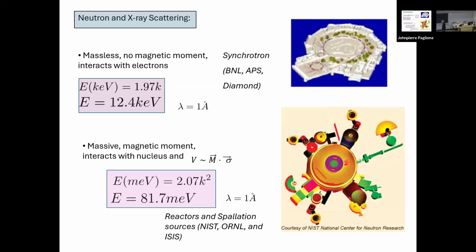So the neutrons actually get produced in copious amounts with the right wavelength and also the right energy scale for the problem that we're interested in. And importantly, for this talk at least, they have a magnetic moment too. So we're sensitive, to first order in interactions through this potential, to the magnetism of the material.